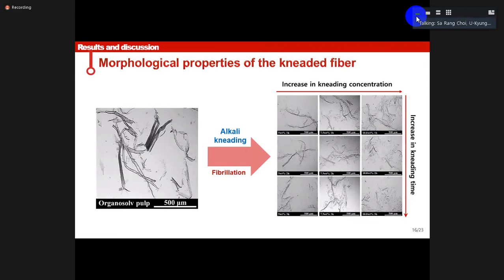To sum up, we did alkali kneading to fibrillate the organosolv pulp on the left. As a result, the fiber fibrillated as shown on the right figure by the kneading process. As the pulp concentration increased and the kneading time was longer, the fiber fibrillated effectively. So, the fiber length and fiber width were reduced the most when kneaded for 3 hours at 10% concentration.